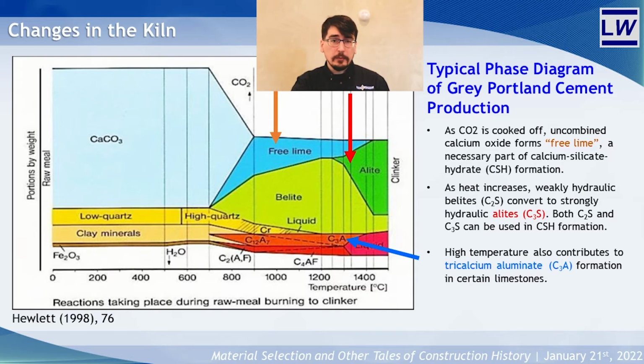C3S begins to form around 1200 degrees C, which is why Portland cement is generally kilned quite hot, at temperatures approaching 1500 degrees C. Tricalcium aluminate, or C3A, on the other hand, is a fusion of alumina and calcium oxides. While C3A does react quickly with water to produce early strength, its presence also opens the material up to increased risks, and so its presence is usually minimized in modern cement production.